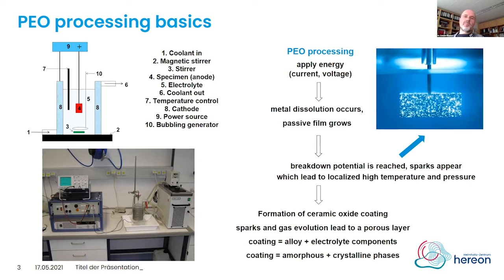However, those sparks are not only beneficial, they basically also damage the coating. There are remaining discharge channels and also inclusions, because there are melted phases in which gases are dissolved. They are also causing this porous layer structure because of gas inclusions and the remains of the sparks. And overall, the coating, one can say, is in most cases a composition of the alloy plus the electrolyte components which we are using. And one can use different processing conditions to adjust between amorphous and crystalline phases.